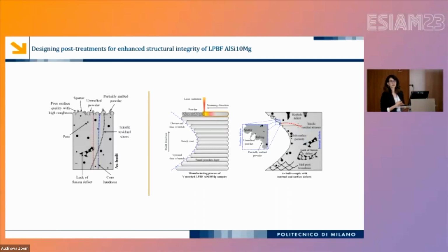In the case of laser powder bed fusion, we have partially melted or unmelted powders that are agglomerated randomly on the top surface of the part. They are causing a lot of issues for a wide range of applications, including wear, corrosion, and fatigue. Even from an aesthetic point of view, this is not the best solution in terms of surface morphology.